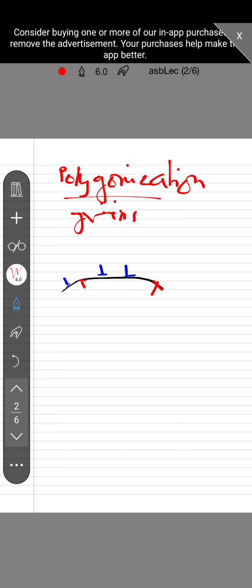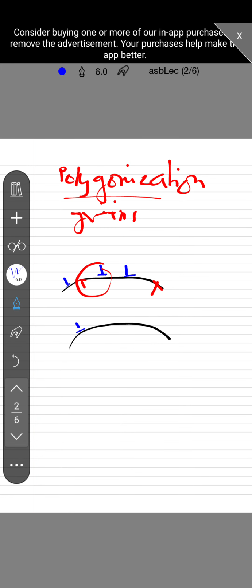Now, when we increase the temperature, what happens is that the dislocations start to annihilate. That means positive and negative dislocations come together and they dissolve. So we are left with a fair number of dislocations, like say this one. The dislocation density has reduced considerably.